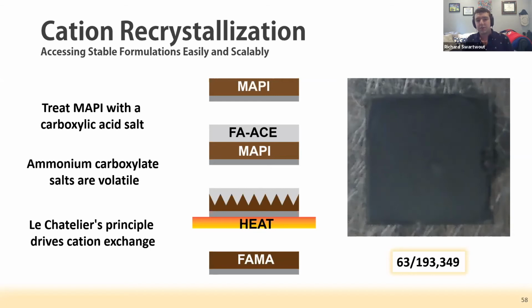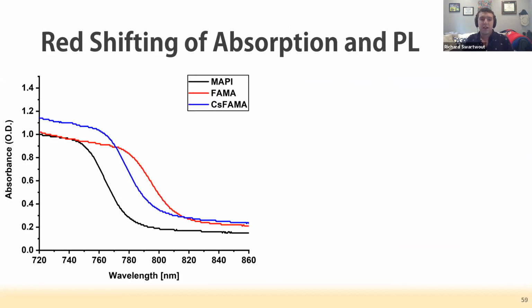From the transition from a methylammonium-based film to a formamidinium-based film, you'd expect a shifting in the band gap, and that's exactly what we see. Between a methylammonium precursor and the exchanged formamidinium—this also works with cesium-based compounds, although I'm not going to talk about that much today—there's a very defined redshift in the absorption edge.